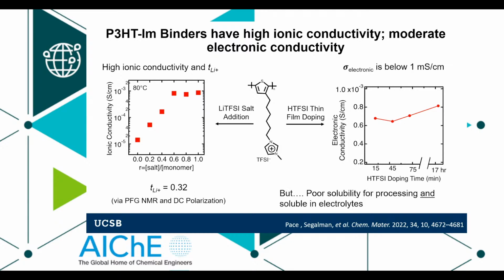And one of the big problems is not just electrical conductivity, it's that conjugated polymers have really poor solubility, right? And so what we did was we took an aromatic backbone, this is a group of chemical engineers, we added a very, very high dielectric side chain. That basically makes you a system that's soluble in almost no solvents on Earth, right? And so the result is that in best case scenario, using some solvents, we can get to maybe 1% solubility. But you don't want to be making macroscopic electrodes out of something that you can only process at 1%, right? It's not going to let you make something that is amenable to a battery.